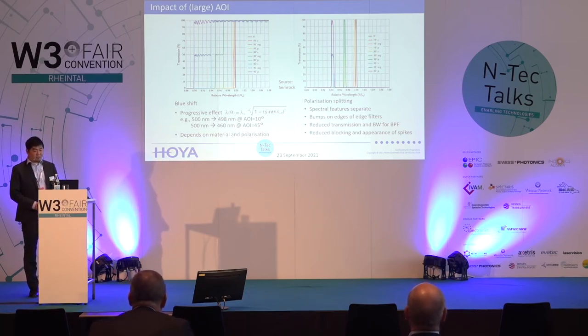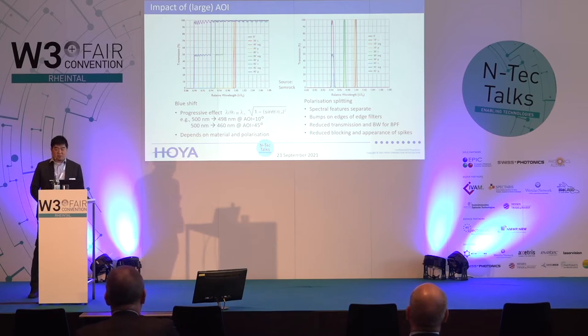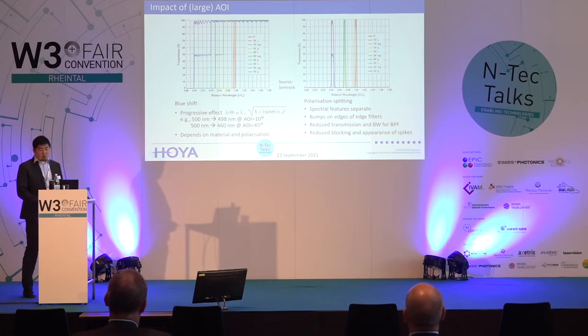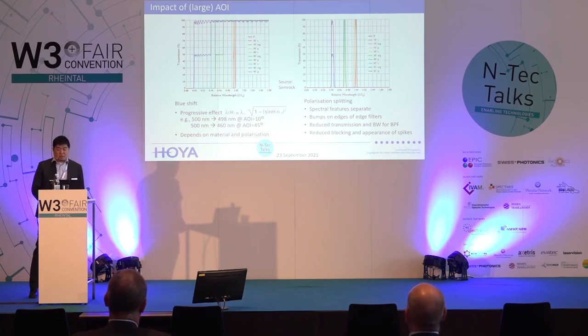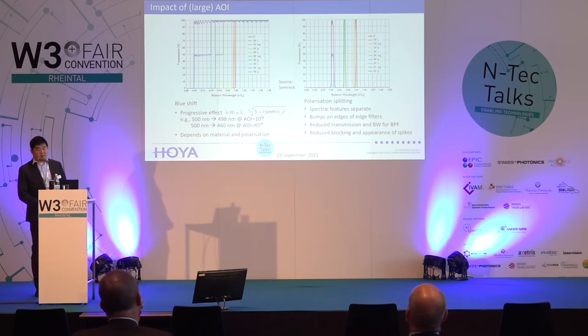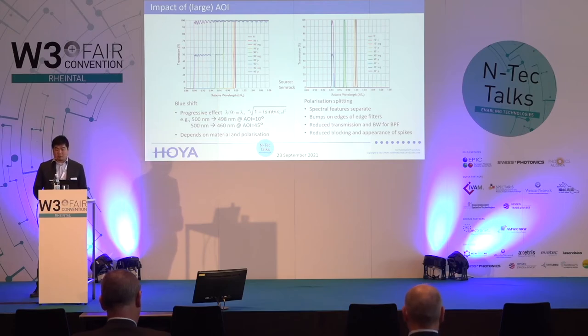This shift itself depends on the material. It is tied to the effective refractive index, and it also depends on the polarization. What is not shown in this slide is that the blocking can also be impacted. You will see reduced blocking and sometimes spikes in the blocking area. So angle of incidence is something to seriously consider for thin film filters.